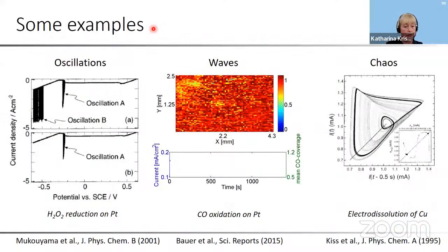Here I show you three further examples, rather arbitrarily selected, because you know that most electrochemical systems oscillate. Here I have an example of the hydrogen peroxide reduction on the platinum electrode. This reaction was intensely studied by Mukouyama and co-workers. The very nice aspect is that they found five different regions of oscillations, where five different oscillatory mechanisms are behind. So it's not that one reaction should always show the same type of oscillatory mechanism. I hope you will understand better in the course of my talk what I mean by oscillatory mechanism. On this sketch, you see two regions of potential where the system exhibits oscillations.